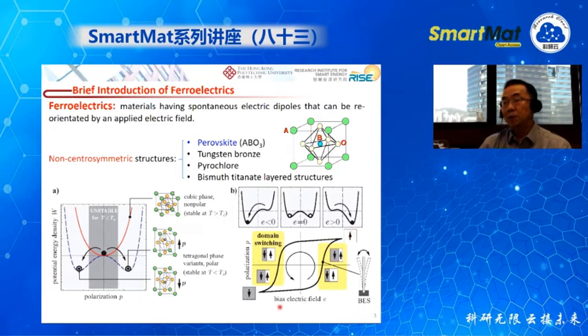So if we measure the polarization as a function of electric field, normally for a ferroelectric material, we get this type of hysteresis loop. When the electric field is removed, the polarization will normally not go back to zero. The reason is the clamping of the domains, because there are a lot of domains existing in the material. So even when the electric field is removed, the clamping of the domains will prohibit the complete randomization of the polarization. So there is a net spontaneous polarization.